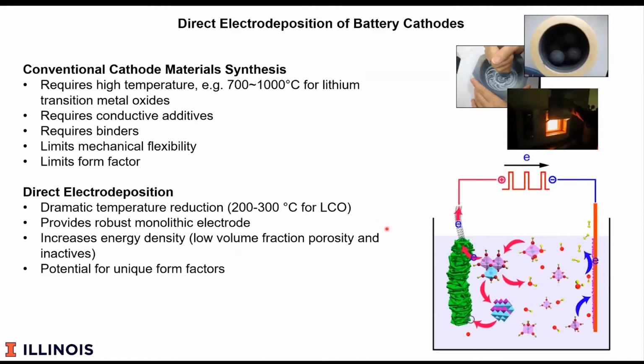So if we compare this, conventional cathodes are made between 700 and 1000 C. They're slurries. They're of course not ground by hand, but they're ground up, and then following grinding, they're mixed with carbon and polymeric binders, and they're tape cast on an electrode. Because of that, they contain a number of materials that don't contribute to the energy, namely the carbon and the binder, and they're limited to perhaps 70 to 80% active material. The rest is porosity in these binders.